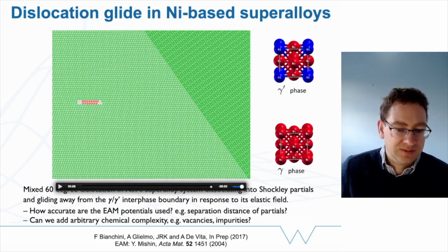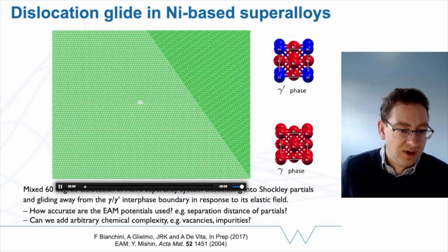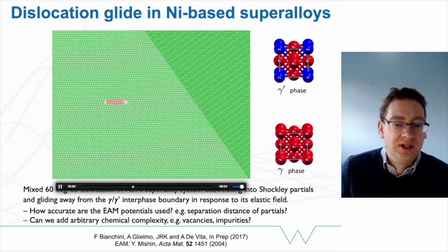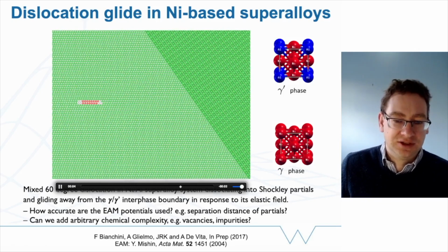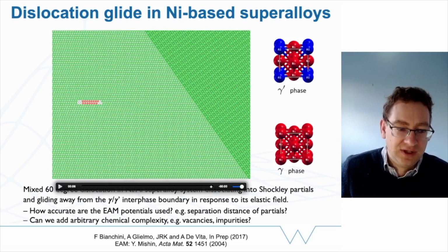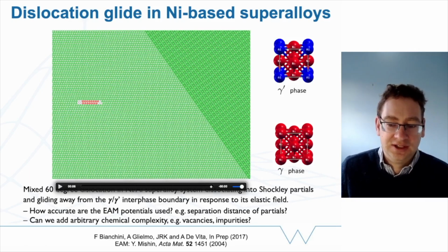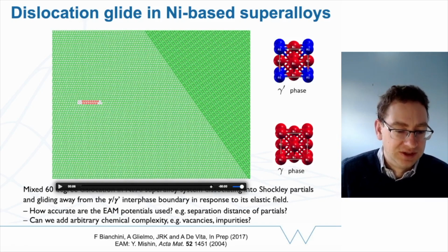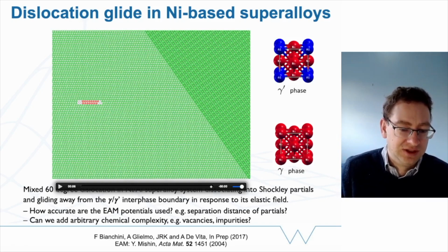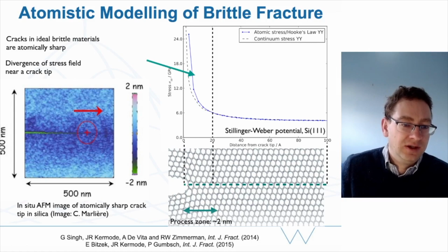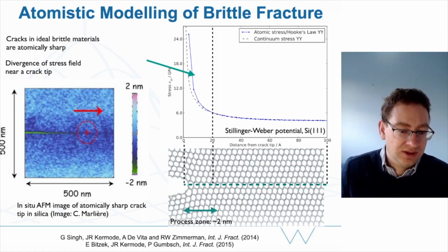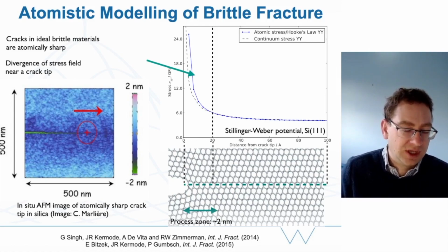The superalloy is made up of a gamma phase, shown on the left-hand side, where my dislocation is moving around, and a harder gamma prime phase which has got extra aluminium in it and is tougher, and the dislocations can't get inside that part. We'd like to understand why that is and improve the properties of the material and improve the accuracy of the modelling as well. In terms of fracture, we'd like to understand how cracks propagate. We know from experiments that the cracks should be completely sharp, like in the picture on the left.